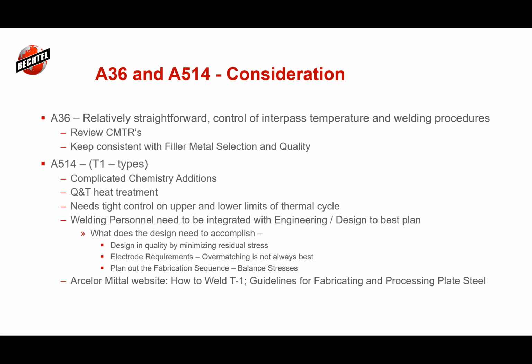Some will have low levels of chromium and nickel, and it's kind of this plain vanilla material that some of the international steel mills will make, and then depending on how they roll it, can increase the strength, and you can turn it into a 572 grade 70, for example, if they do some controlled rolling. All I bring that out is always consider what your CMTRs are if you know what you're welding on, and you might be able to eliminate a surprise before it happens.